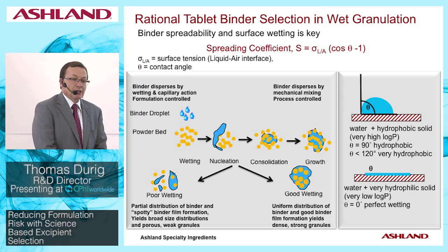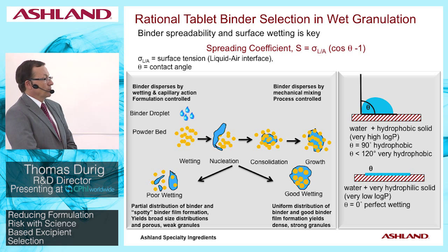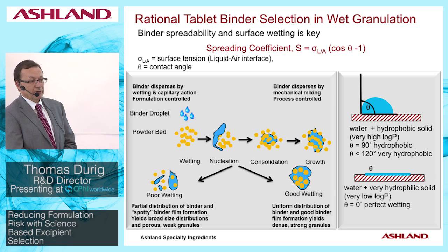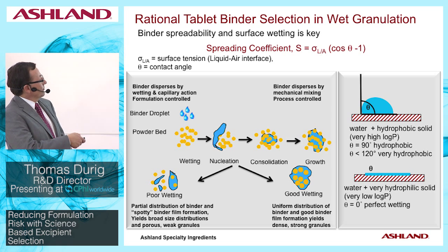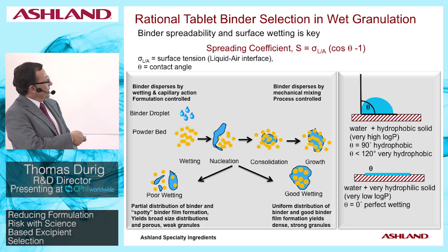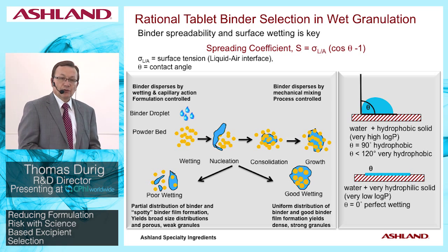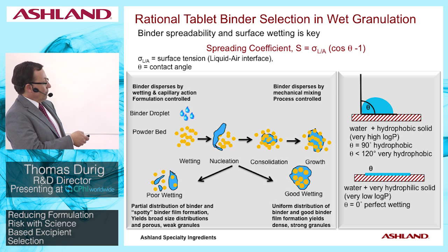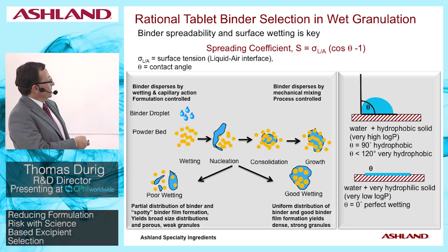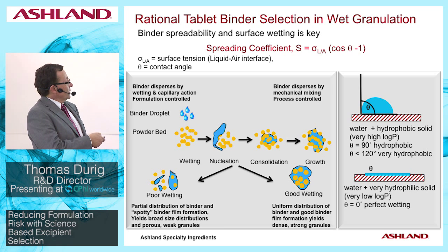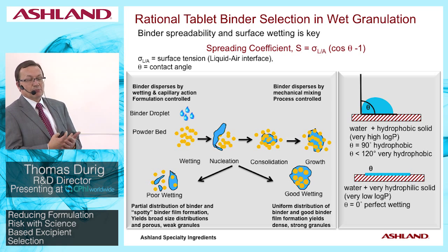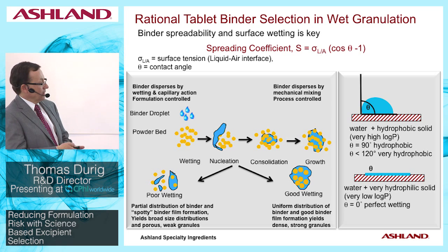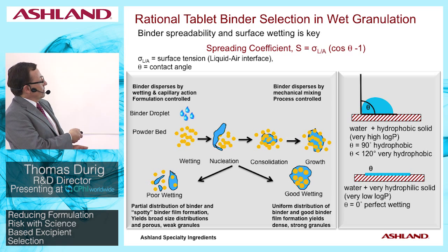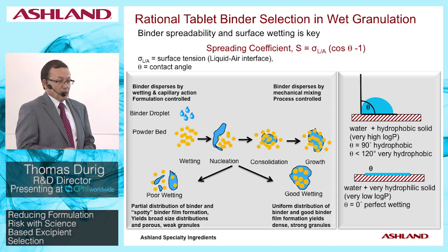Another example of using a science-based polymer selection approach would be the choice of tablet binders for wet granulation. Here we have a simplified schematic of the mechanism by which granules are formed during wet granulation, and it starts by the binder droplets contacting a powder bed, and if the binder solution is spreadable and able to wet the API and the formulation contents, then one tends to form a smaller nucleus, which then grows into a larger granule.